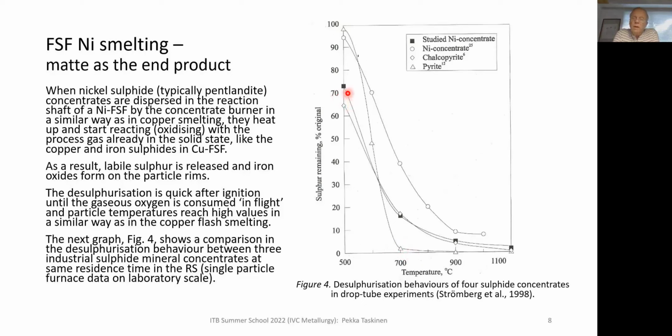and chalcopyrite and a nickel concentrate are less reactive, and from a literature source, this nickel concentrate was even less reactive. It lost its sulfur slower than the other nickel concentrate, and also much slower than the pyrite concentrate.